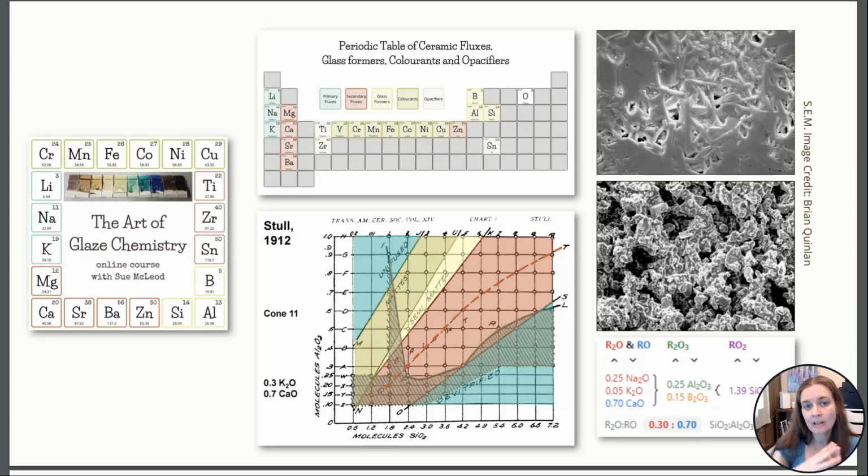Well, if they haven't completely melted at the time that the kiln shuts off, they just kind of fuse together and you may end up with a matte glaze that's just an underfired glossy glaze. So this is a scanning electron microscope image of a properly formed matte glaze, which is where the glaze has completely melted into a liquid.